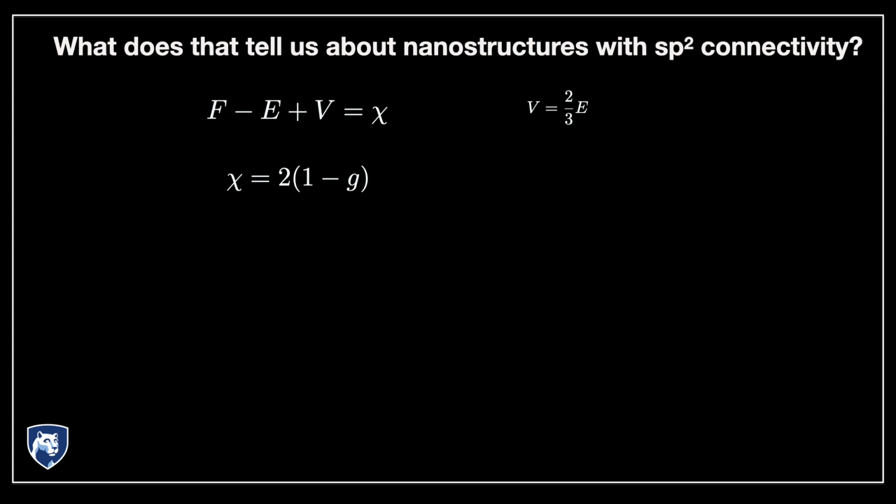We can also relate the number of edges, or again, number of bonds, with the size of the different rings. So here I introduce a new notation, alpha I. Alpha I is the number of rings that contain I edges. So we have this sum of I alpha I. We need 1/2 because, of course, we do a double counting, right?